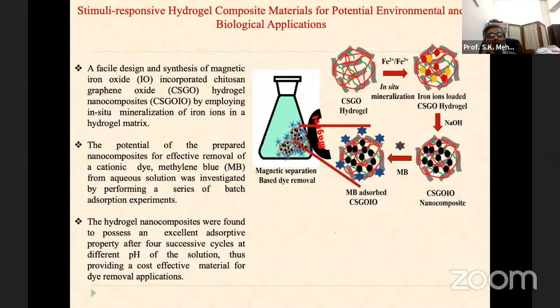So for this, we tried to design and synthesize a magnetic iron oxide incorporated chitosan graphene oxide hydrogel. So we created a chitosan graphene oxide hydrogel, and an in situ reaction, in situ mineralization, was carried out, and we incorporated magnetic iron oxide inside it in situ. So we get iron loaded hydrogel nanocomposites. So this is CSGO hydrogel, which has iron oxide.